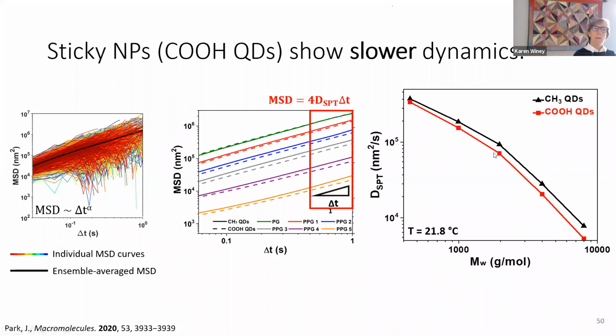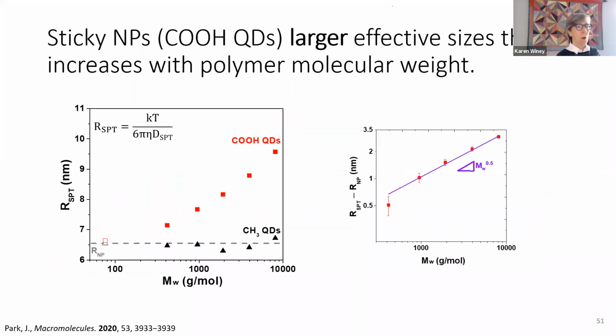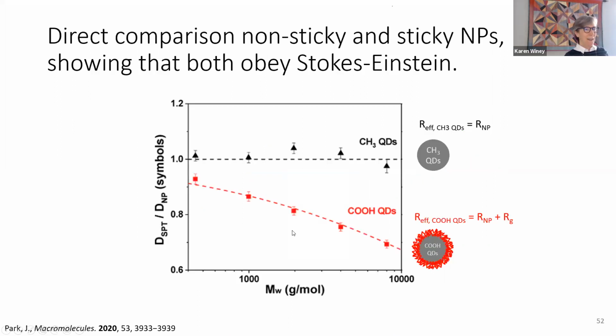Okay, now we have two sets of particles, sticky is in red, non-sticky is in black, and 5 different molecular weights. And we see that the sticky particles are slower. And as we saw in the polymer melt before, the effective radius or size of the sticky particles is increasing with molecular weight, power law to 1/2. But the new data is that the non-sticky ones are not. So it's a non-result. They're behaving just like Stokes-Einstein, and that we can see here.